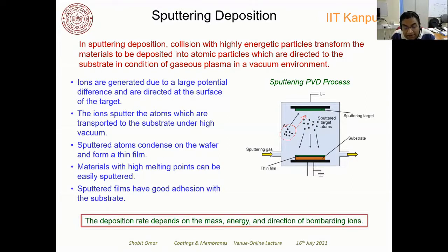Well, the deposition rate depends on the mass, energy, and the direction of the bombarding ions. So this mass is very important. Atomic mass of the sputtering gas is very important. What is the energy, and that depends upon the electric field that you apply here, and of course what is the direction of the bombarding ions on the target surface. That will basically decide the deposition rate of the thin film on the substrate.